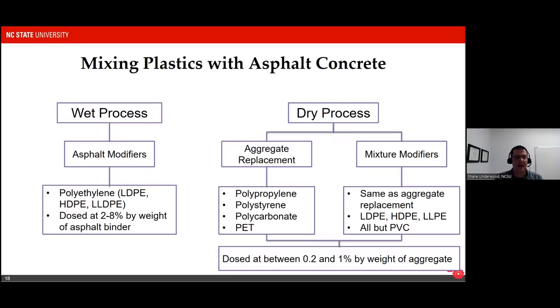That's typically done at a dosage rate of about 2 to 8%, and we'll generally use low density and variants of low density polyethylene. So we're generally going to be using, for wet process analysis, polyethylene materials.